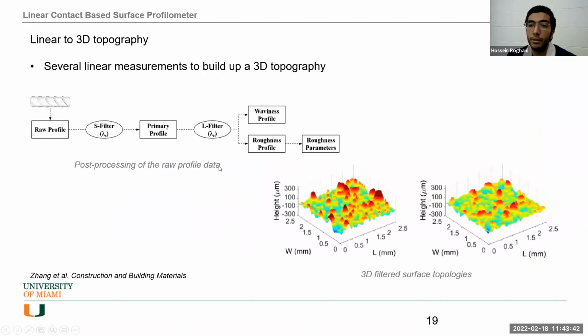So to address this problem, one way is to do several linear measurements. For example, choose a 2 millimeter by 2 millimeter area, for example, between two lugs of your reinforcement, and do several linear measurements. For example, every 10 microns, do one measurement and go to the next line, and at the end, with omitting all the noises in the data that you receive from your surface profilometer, you can build the 3D topography and say, okay, here is my surface profile, and you can compare different types of the rebars together and come up with the surface roughness parameters.